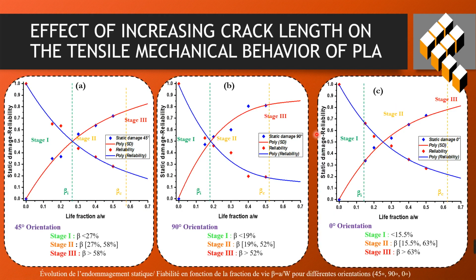The figure shows that the 3D printed samples follow a similar pattern in 3 distinct stages of damage, regardless of their orientation. However, the critical life fraction varies slightly depending on orientation, indicating the effects of layer orientation on the initial strength, and also on the damage evolution of the material.